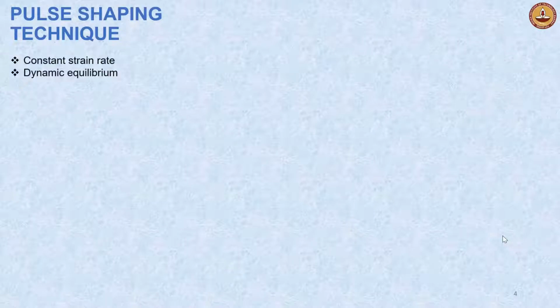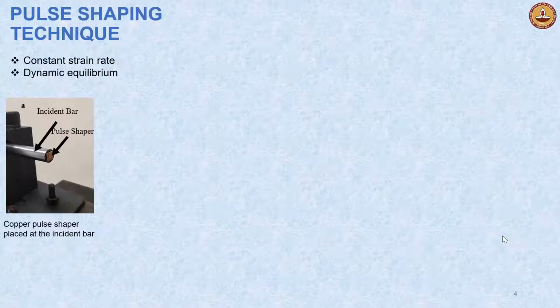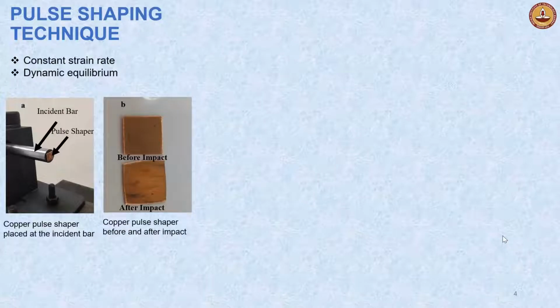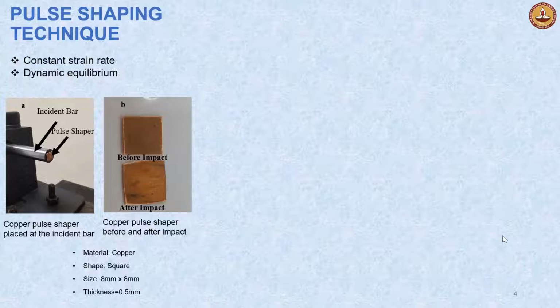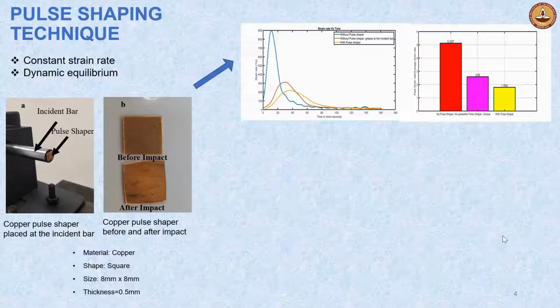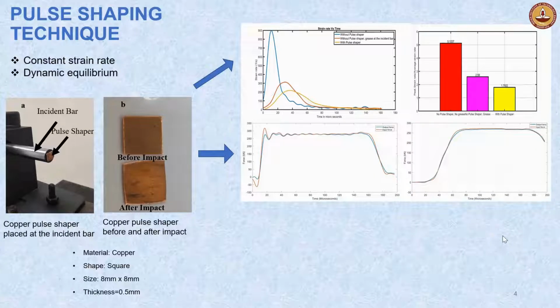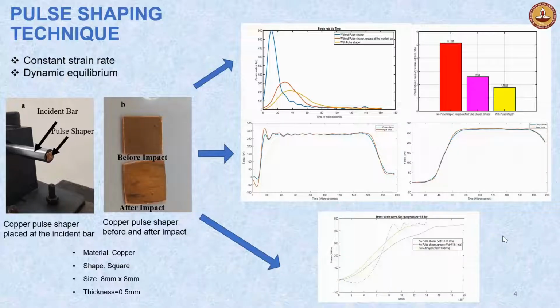We used a thin copper plate as the pulse shaper, which is placed at the end of the incident bar. Copper pulse shaper converts the trapezoidal waveform into ramp-shaped signal. The effectiveness of the pulse shaper is also studied by considering the ability to achieve constant strain rate and dynamic equilibrium. For this, peak strain rate to average strain rate ratio was used, and this value improved from 5.1 to 1.7 when we used pulse shaper. Input-output forces on the specimen face also matched well with the use of pulse shaper. Noise in the stress strain curve is also reduced in the experiments with pulse shaper.